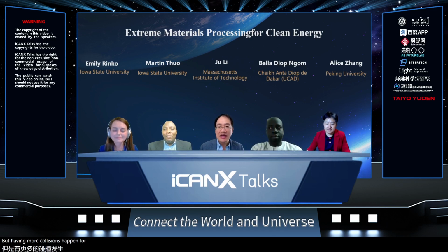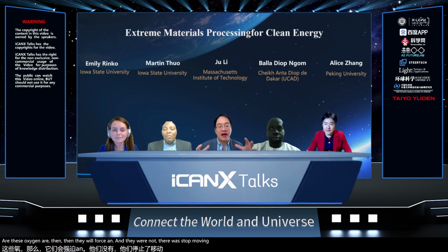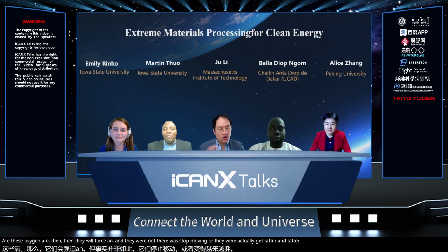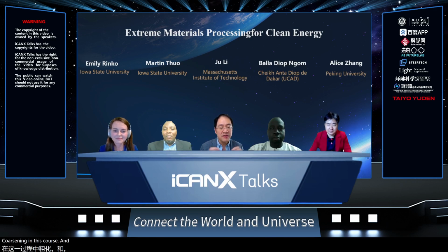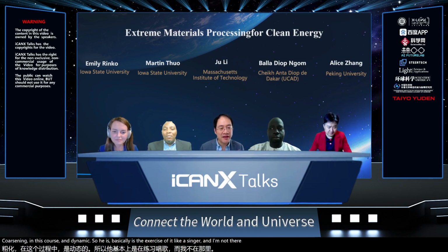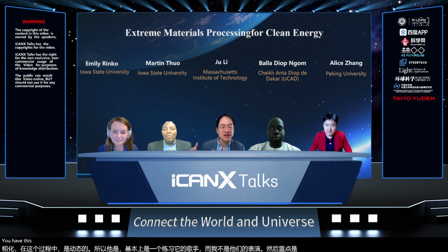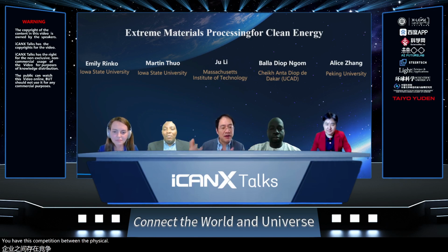So indeed, if we don't feed it this oxygen, then they will coarsen and they will stop moving, and they will actually get fatter and fatter in this coarsening dynamic. So it is basically like if they exercise, they get thinner and they're active. And the whole point is you have this competition between the physical Young-Laplace kind of driving force for coarsening balanced with the desire to have more surface area to do the chemical catalysis.